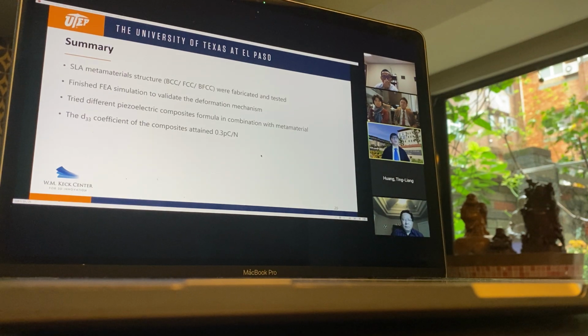Okay, so in summary, metamaterial structures like BCC, FCC, BFCC were fabricated and tested in this project. And FEA simulation was used to validate the deformation mechanisms. And we tried different piezoelectric composite formulas to fabricate a better composite. So the piezoelectric coefficient we got from the composite is 0.3 picocoulomb per Newton.